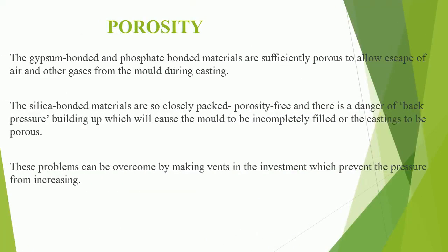Now, in the ideal requirements of investment materials, we discussed that the investment materials should be sufficiently porous to allow gases to escape, and the gypsum bonded and phosphate bonded materials have this property. However, the silica bonded materials, because they are closely packed, are porosity free, and there is a danger that the pressure may build up inside, which can cause the mold to be incompletely filled or the casting to be porous. So what we have to do is physically make holes or vents in the investment ourselves so that this prevents the buildup of gases during the casting process.